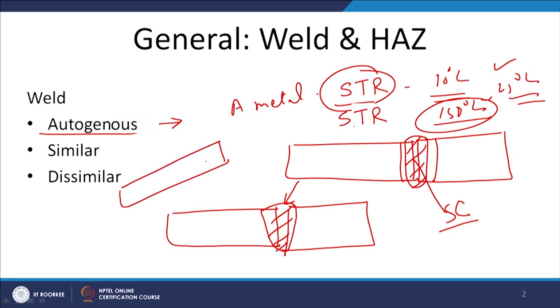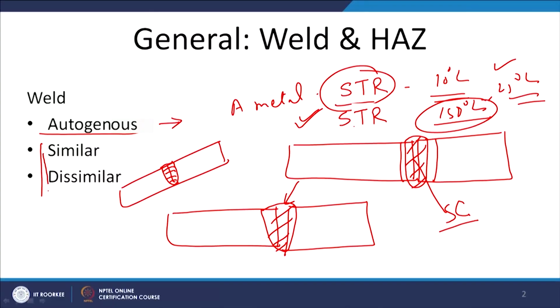direct melting of the base metal may not always be feasible if the metal has a wider solidification temperature range, or if, due to high hardenability, it leads to embrittlement of the weld metal. So, it will be better to use an electrode or filler metal of lower hardenability, like austenitic stainless steel or low carbon steel filler. So, it may not always be favorable to have the autogeneous weld through melting of the faying surfaces and subsequent solidification of the weld metal for producing a weld joint. Sometimes it is good to have fillers and electrodes either of matching characteristics or of completely different characteristics.